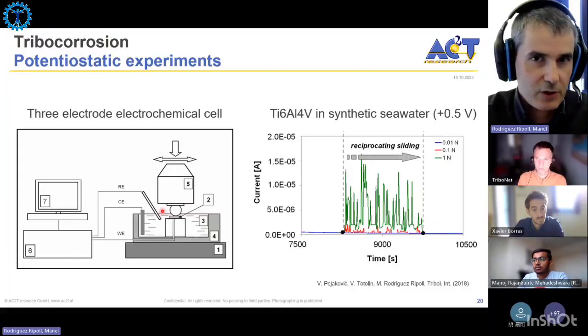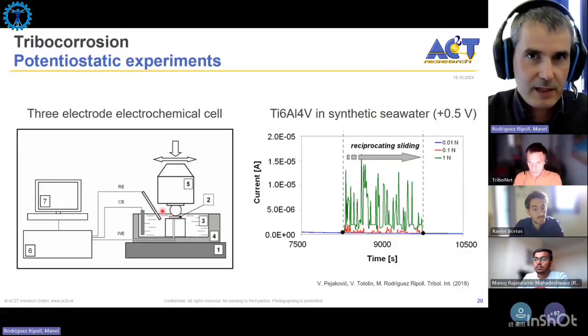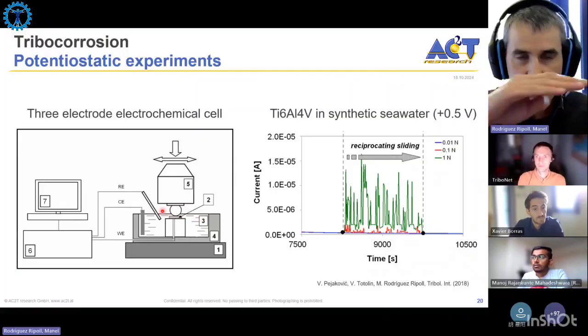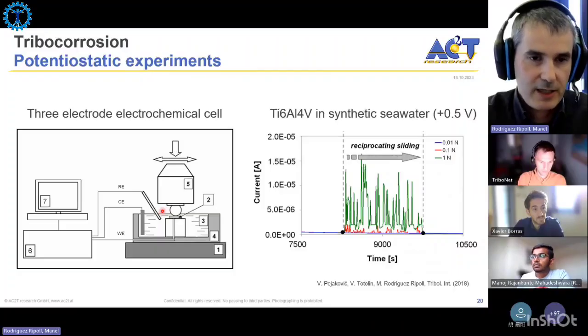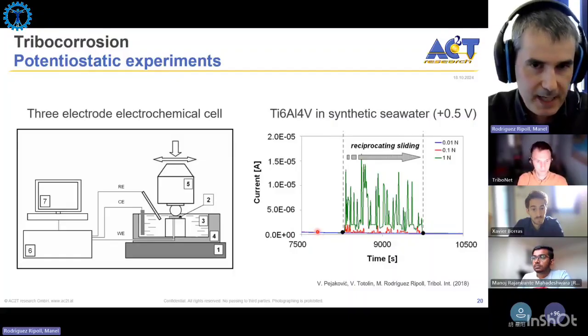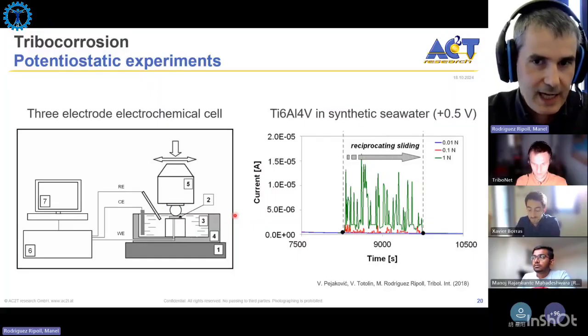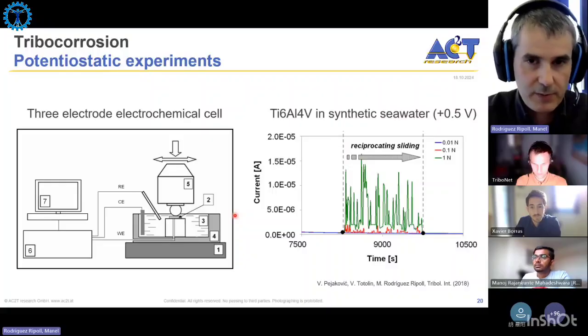in this polarization curve, we have seen that for passive materials in this semi-logarithmic scale, in the passive domain the current density is independent of the applied voltage and is very low. It means that if we apply a passive domain voltage, for example here, plus 0.5 volts, to titanium in synthetic seawater, the current is very low because we have this dissolution, but it's very small compared to active metals. But as soon as we start rubbing, we trigger corrosion, and then we can have a higher current that we can measure with the potentiostat in the same way that we did in the polarization curve.